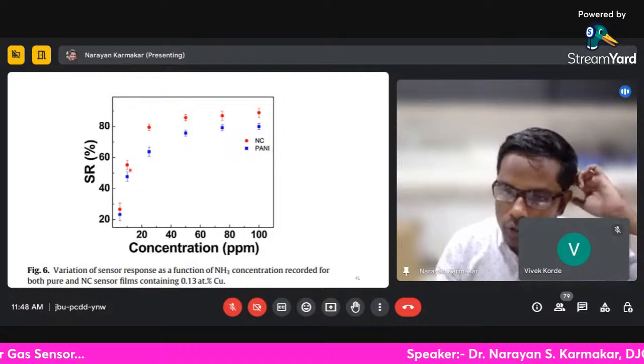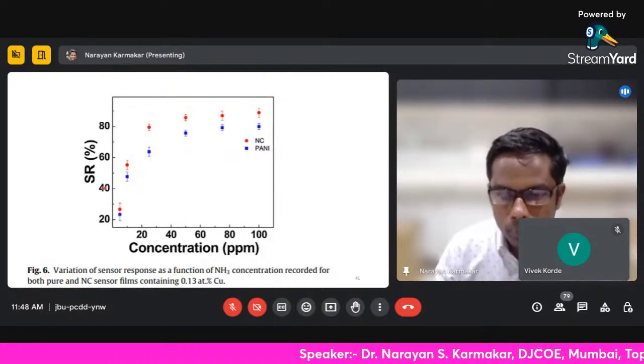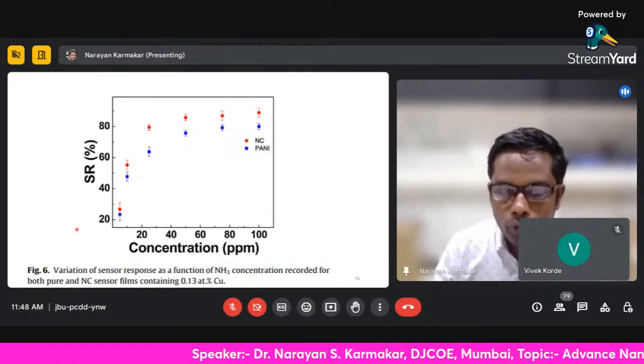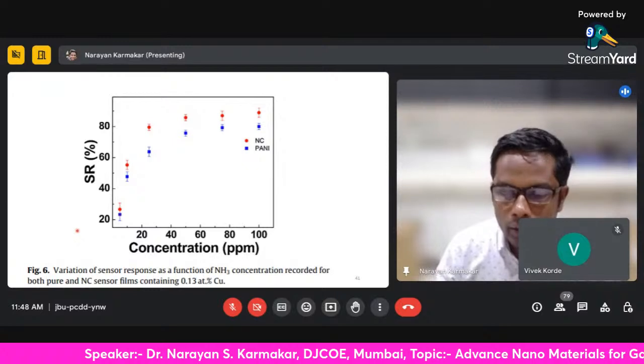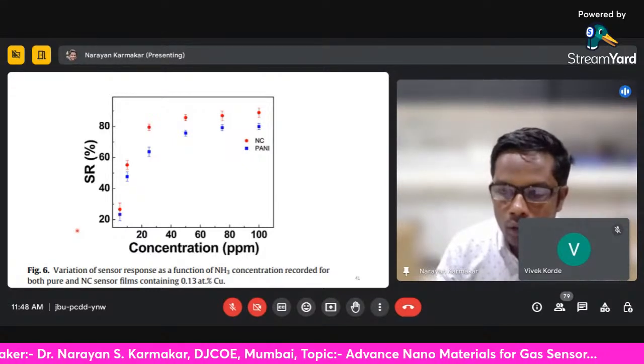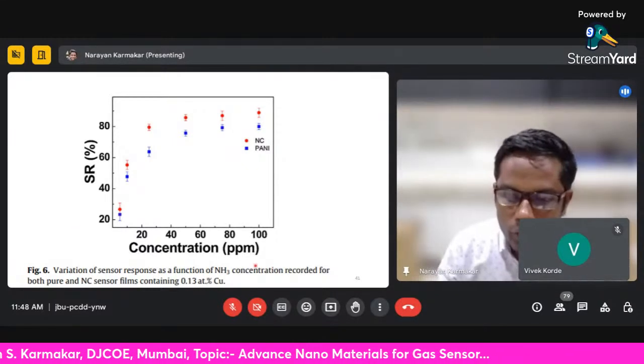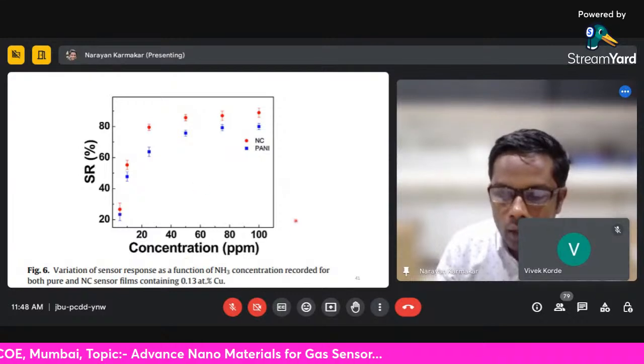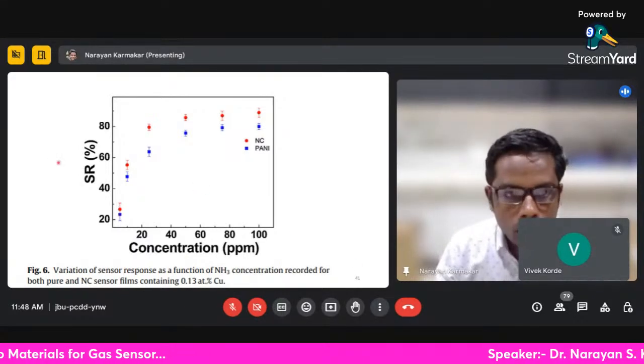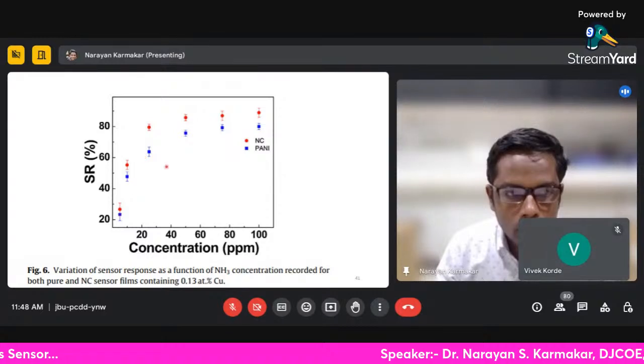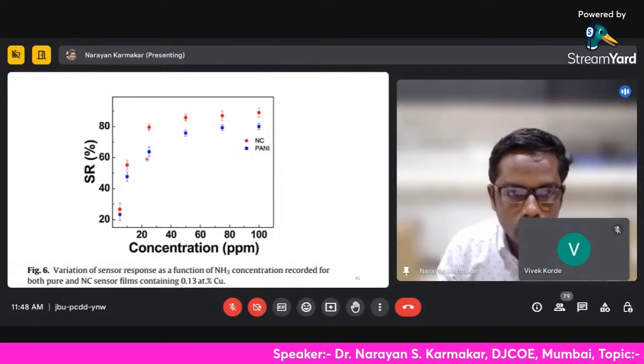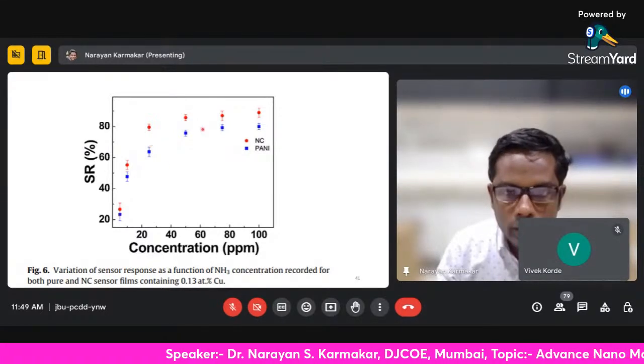At high concentration, the decrease in sensor response can be attributed to the shunting effect between the metal and the semiconductor. The part of the sensor resistance that is shunted will not contribute to the response of both the adsorption and desorption process, and after a certain point, it saturates.